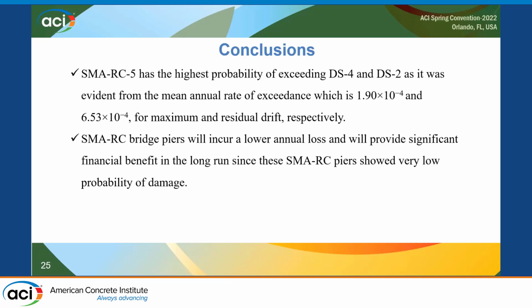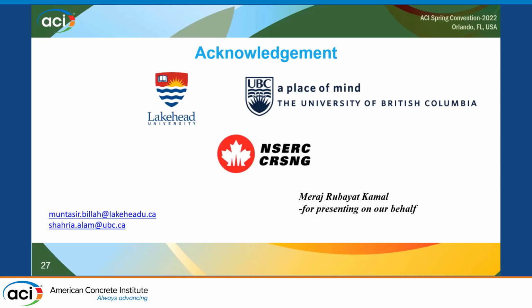But SMA-5 had the highest probability of exceeding damage state 4 and also damage state 2, as we can see from the graphs I have shown before. So to conclude, we can say that SMA-RC bridge piers will have the minimum annual loss and provide a significant financial benefit, we feel, in the long run, because they had very low probability of damage. So this concludes our slide.